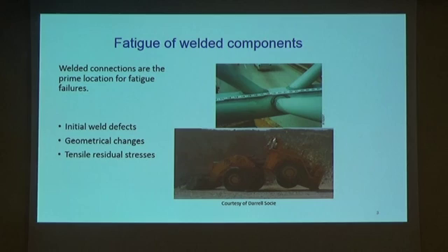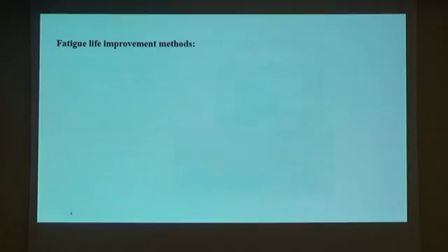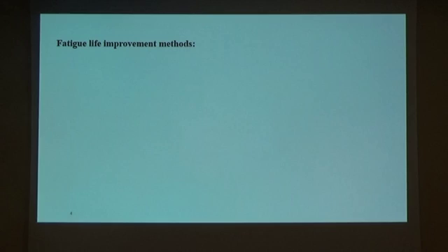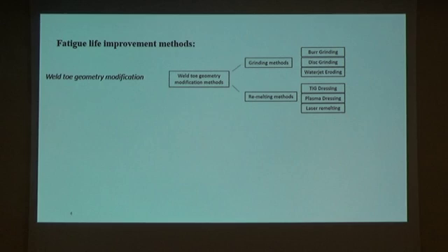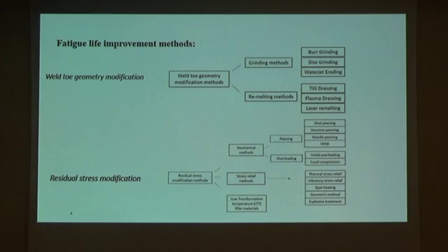The third reason is that we have tensile residual stresses because of welding. Therefore, we need fatigue life improvement methods in order to increase the fatigue life of welded components. One main group of methods is weld toe geometry modification methods, and we also have residual stress modification methods to increase the fatigue life.